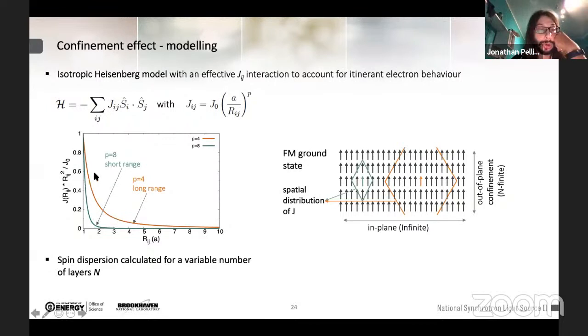If we want to better visualize how this J interaction changes as a function of space, we investigate two possible values. One is P equal to 4, which is a long-range interaction. The other one is P equal to 8, which is a short-range interaction. The short-range interaction is essentially limited to the nearest neighbor, whereas if we take the long-range interaction, we have a much wider range of exchange.